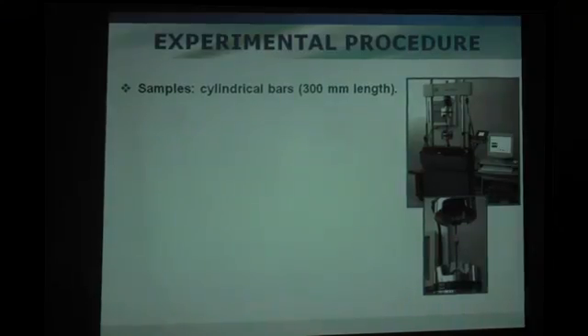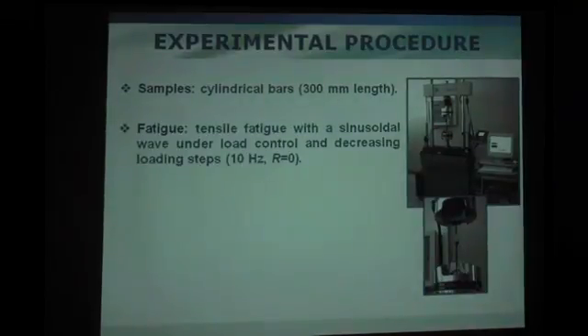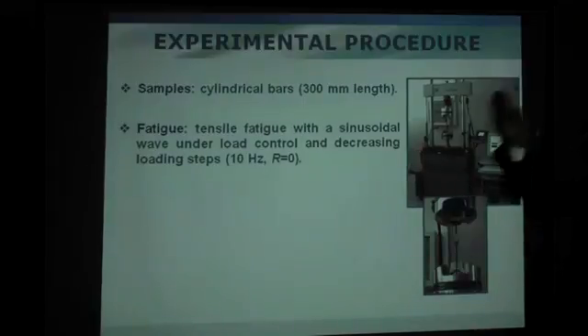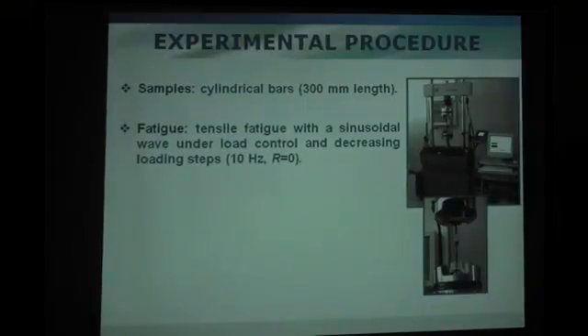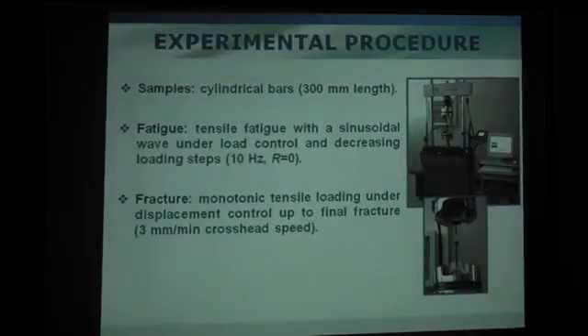Now the experimental procedure, we use samples as cylindrical bars of 300 mm length. This is the universal testing machine for fracture mechanics analysis. The testing, we pre-crack by fatigue, tensile fatigue with sinusoidal wave under load control and decreasing load in steps. Typical frequency of 10 Hz and R ratio equal to 0. No overload. We don't believe in plasticity crack closure, as you know, but we discussed in Malaga heavily.